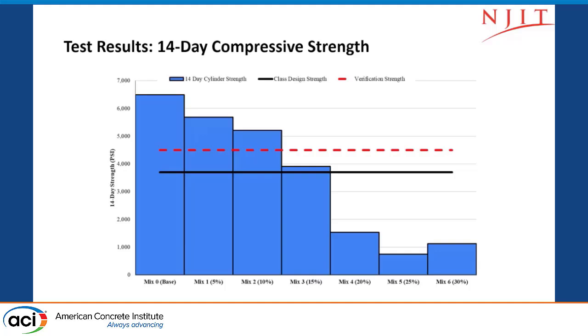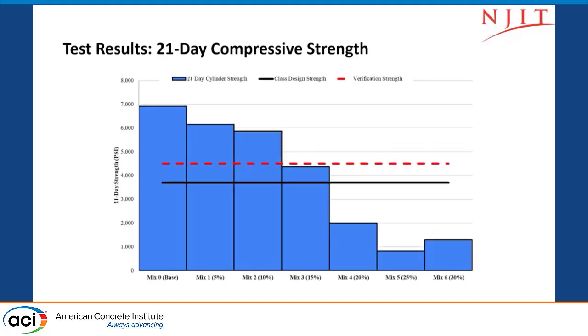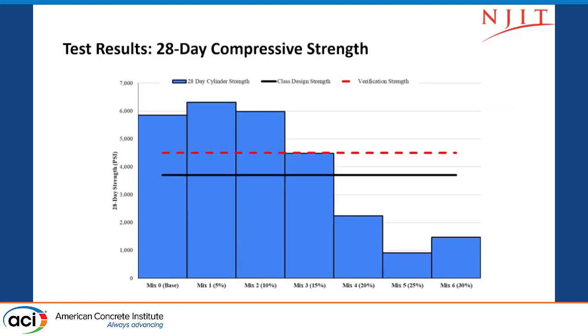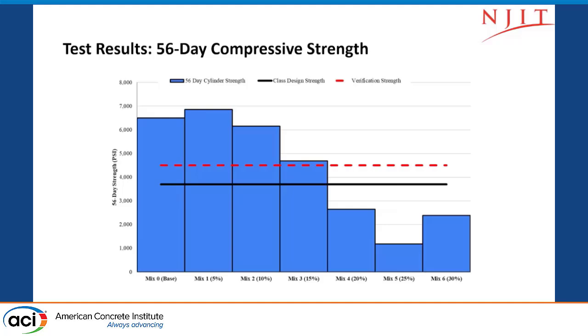This is the 14-day compressive strength, and we did the 21-day compressive strength, and we see that we are getting higher. For 28-day compressive strength, we are getting higher up to almost 15%, and then after that everything is collapsing, going nose down. This is the 56-day compressive strength, again up to 15% we are on the safe side. 15% is on the verge, and then after that everything is going down.